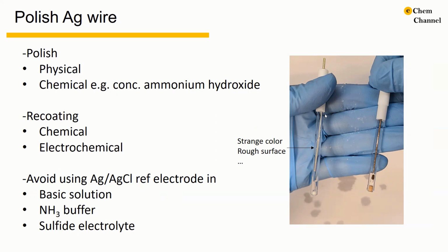So sometimes before you use the silver reference electrode, you may notice that the color of the silver wire is different, or the surface of the silver wire is not smooth. In this case, we need to polish the silver wire in order to offer a standard potential. We can do physical polish as well as chemical polish. For physical polish, we can just simply use a fine sandpaper. For the chemical polish, we can use concentrated ammonium hydroxide.